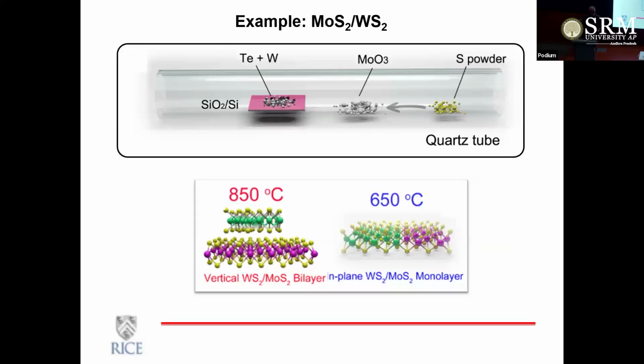In any case, even if you're going to stack, it will be quite challenging to kind of build a stack of certain thickness because each one is only a single atom thick, right? I can imagine creating a stack by picking and placing every layer, right? But how long will it take to create a 5 nanometer stack? And there are other practical challenges in doing that. So one thing we were interested in doing from the beginning was to be able to create these stacks in one shot. So introduce all the precursors to grow.